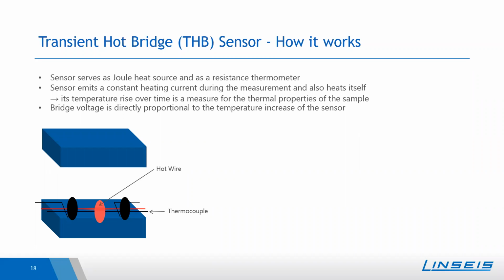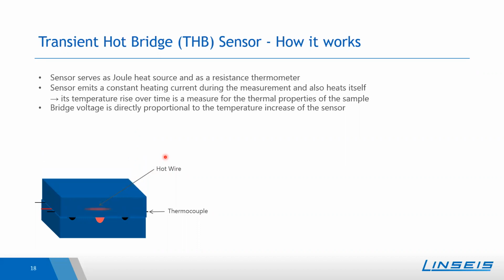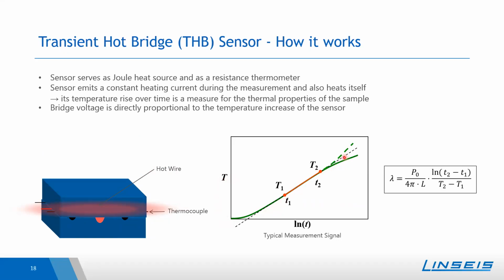Especially for the THB sensor and the QSS sensor, which are connected to a bridge network, one does not measure the temperature increase directly, but one measures the bridge voltage, which is directly proportional to the temperature increase. Here you can see an illustration. During the measurement, one uses the sensor, which is basically a hot wire and a thermocouple. The sensor needs to be completely surrounded by the material. So typically one needs 2 sample pieces and sandwiches the sensor in between. During the measurement, the sample will be heated by the hot wire, and the thermocouple recognizes a temperature increase with time. Based on that, one can determine the thermal conductivity.